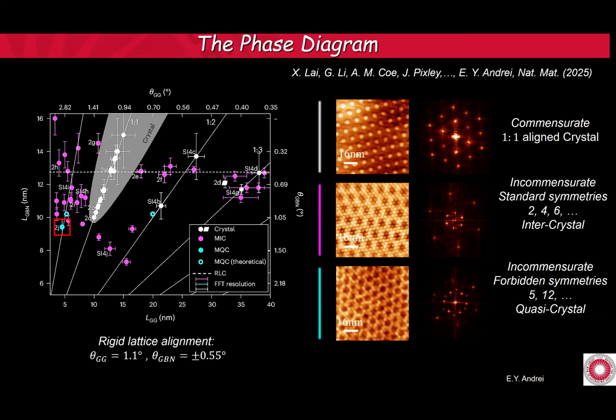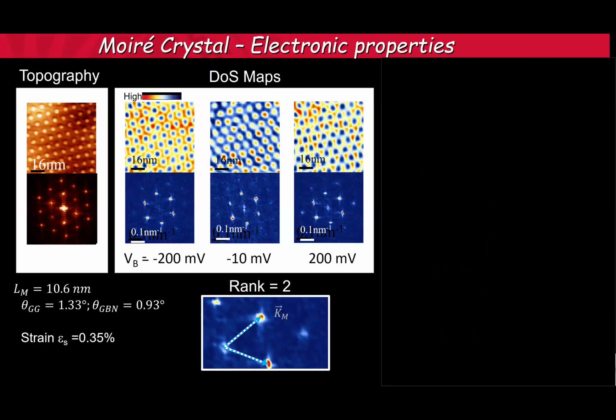Okay. So the next thing to ask is, what does that do to the band structure? What does it do to the electronic properties? So here we have a sample that has a little bit of strain. It's a one-to-one align. This is a topography. It looks beautiful. The 6-fold symmetry in the Bragg peaks. And then you do the density of states map. You take the Fourier transform, and you see that actually no matter where we go, at what energy we go, you always see the same kind of Bragg peaks. They don't change. The intensity stays kind of the same.